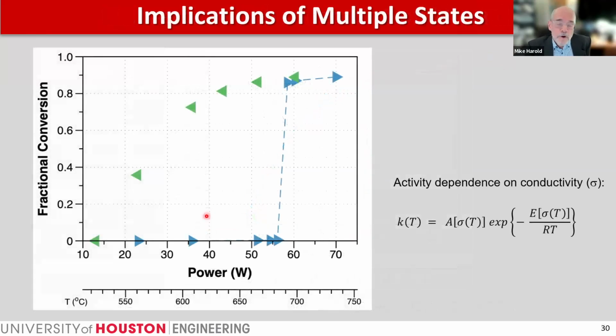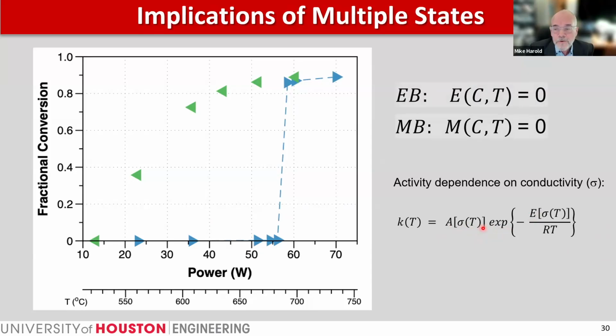Now, interestingly, from a fundamental standpoint, we have to answer this question, which we've not yet answered, which is how can we actually predict the existence of multiple steady states for an endothermic reaction? And what I'm suggesting here is something that we still need to do, but we believe that we're getting catalytic enhancement due to the flow of electrons through the catalytic layer, which is serving to affect the activity of the nickel catalyst. And one way of testing that would be to semi-empirically make either the activation energy or the pre-exponential factor a function of the conductance, which itself is a function of temperature, and to put that into the energy and material balances and see if the resulting mathematical model exhibits or predicts multiple steady states. We've not done that yet, but we will be attempting that in the coming weeks.